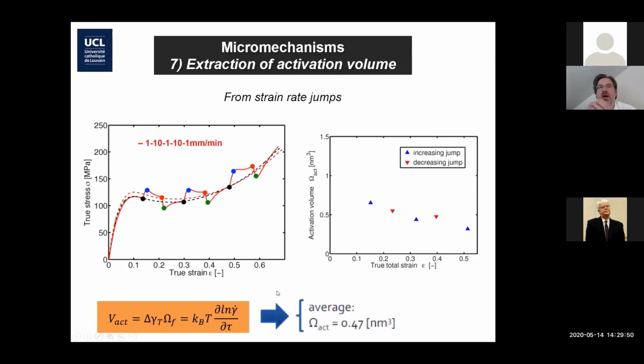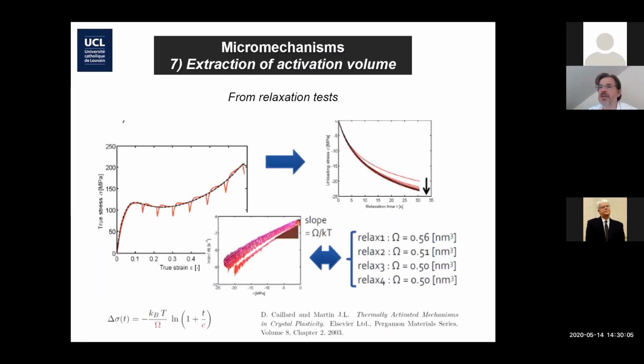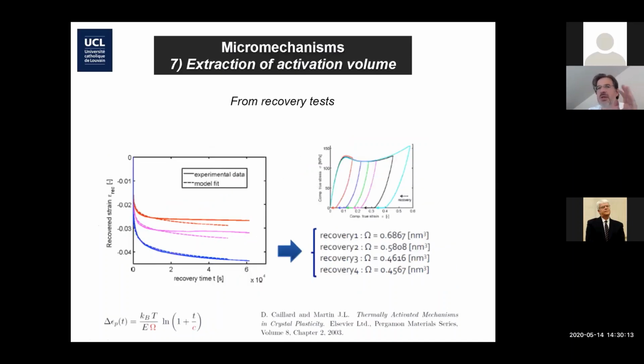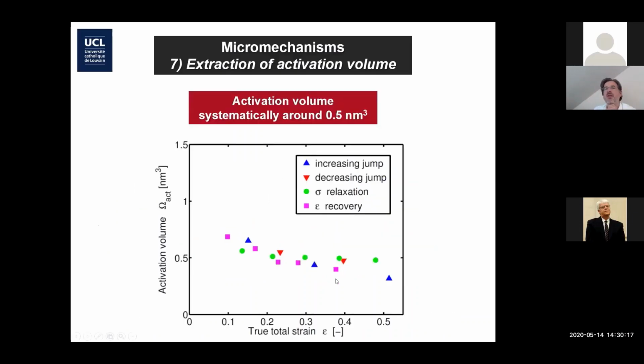It is an imprint of the fundamental mechanism taking place at the nanoscale and giving rise to the plasticity mechanism. And I will come back to that later. Typical value that is obtained is 0.5 nanometer cube. And there are other ways to measure this quantity through relaxation tests, through recovery tests. You have to make some assumption, but I will skip that for the sake of time. But at the end of the day, when we combine the jump test, relaxation test, recovery test, and we perform that at different true total strain, the activation volume we measure changes a little bit with the strain, but not very significantly, and is always about 0.5 nanometer cube, which means that there is a phenomenon taking place at that length scale triggering the permanent deformation of the material.